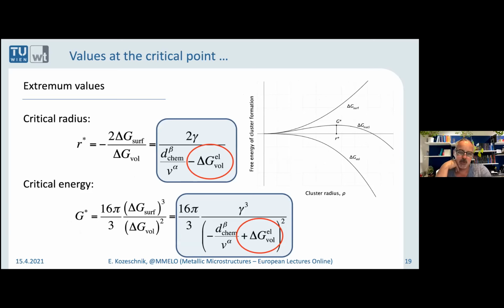Nucleation theory should be extended. The critical quantities are now adding also the stress energy. And you can see it has a different sign compared to the chemical driving force. So it's always reducing the chemical driving force and actually increasing the nucleation barrier.